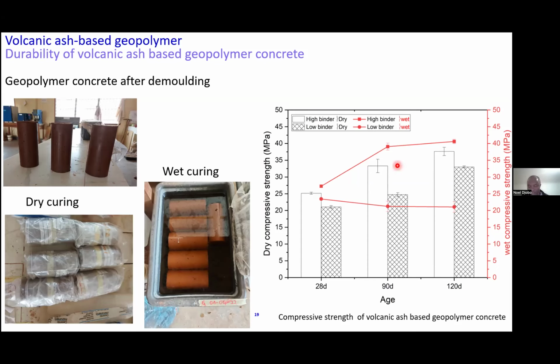So in this graph, on the right side, I have tested the mechanical property of the concrete blocks that I have made and cured in those two conditions. The dry compressive strength is the compressive strength measured in this concrete block, and the wet compressive strength in red is the compressive strength measured from this one. What you see here as a high binder and a low binder simply means that for making concrete, you have, as I said, a binder, which is a glue, and you add sand and gravel. If you add more binder, you will also increase the cost of your concrete. If you add low binder, you will decrease the cost of your concrete.